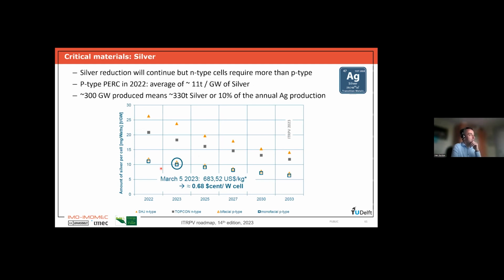What the industry thinks about this is that the silver reduction will continue, but typically for N-type cells, more silver is needed than for P-type. If we look at P-type PERC in 2022, we typically needed 11 tons per gigawatt of silver, whereas we should only use 6 or even 2. And 300 gigawatt of production in 2022 means that we used around 330 tons of silver, corresponding to 10% of the total amount of silver produced that year. And cost-wise, it is also not negligible. The silver that we use is costing us around 0.7 cent per watt.